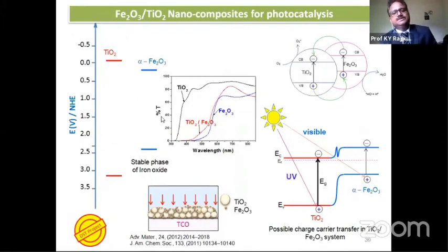If you make a composite between TiO2 and iron oxide, for example, then the band gap of iron oxide is in the visible, and the band gap of TiO2 is in the UV. The band positions are such that the conduction band edge of TiO2 is higher than the conduction band edge of iron oxide, and the valence band edge of TiO2 should be lower than the valence band edge of iron oxide. This is before contact and this is the energy diagram after contact. Due to charge transfer, band bending takes place and a built-in potential occurs, and UV is absorbed in TiO2 and visible is absorbed in iron oxide. In this way, both these semiconductors take part in the photocatalysis reaction. So this is one way to improve the photocatalytic activity.